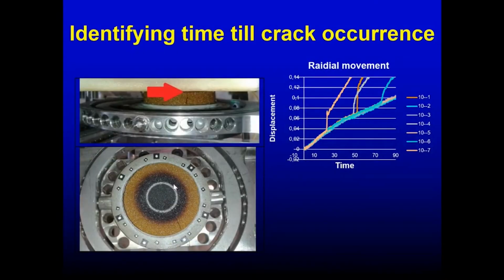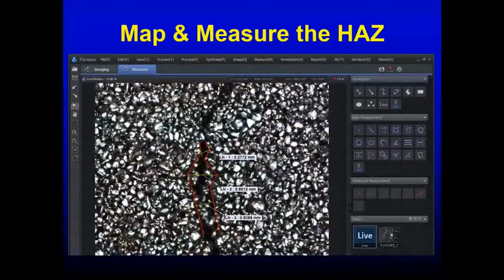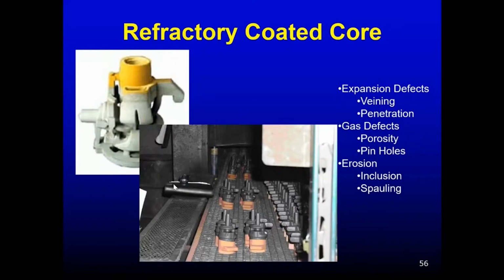So we know how long it takes for that crack to develop. If the sand binder system cracks and there is liquidus in the metal, that's where we get a vein, that's where we could get penetration. But if the crack occurs much later in the test and the iron has skinned over or solidified, then we don't have to worry. That crack will help us shake out. So we have evidence, we measure that crack propagation relative to the heat affected zone, right? Again, there are other additives, as I mentioned, engineered additives that we can place into the recipe.